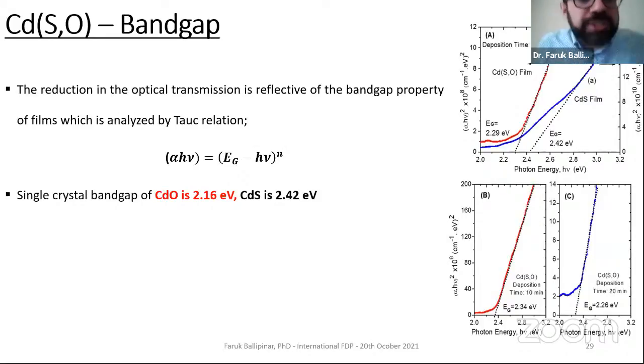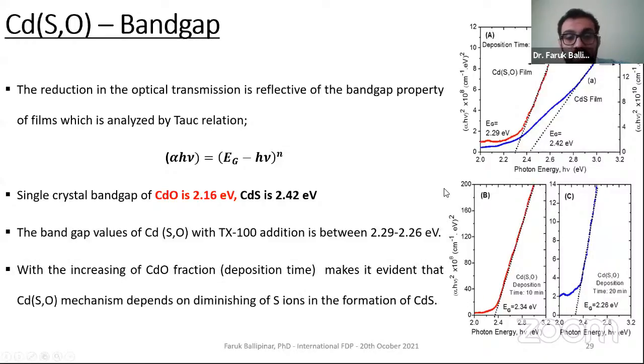Again, the Tauc relation is the common technique for band gap calculation from the transmission data. The literature, DFT, and some experimental results show the cadmium sulfide band gap is 2.42 eV and cadmium oxide is 2.16 eV. Based on the results we calculated from the transmission data, our cadmium oxysulfide band gap value is between these two.